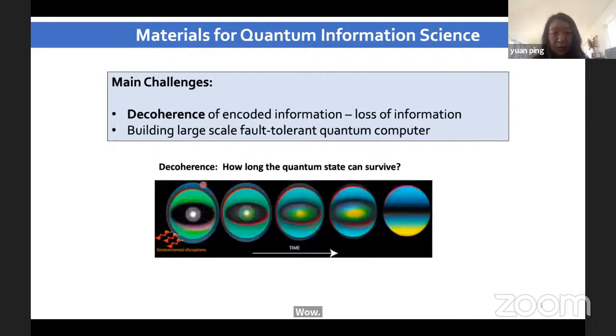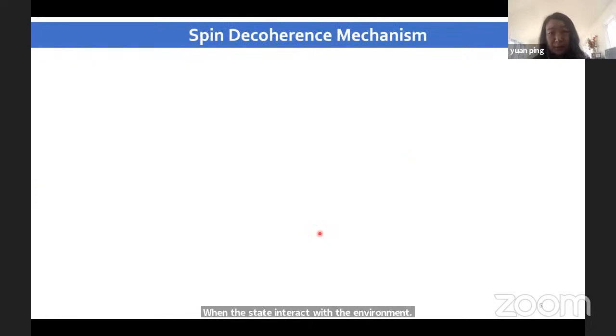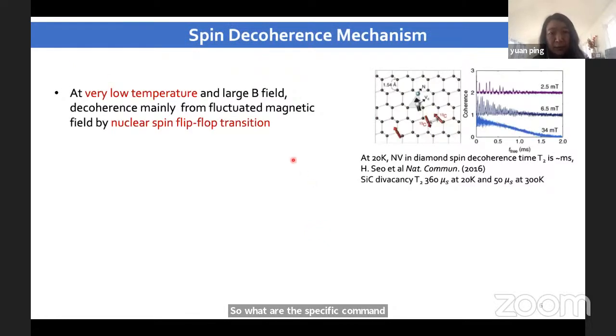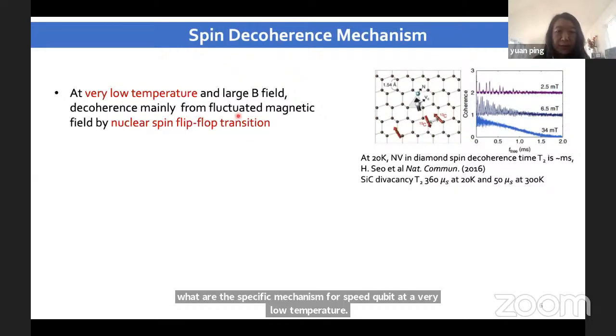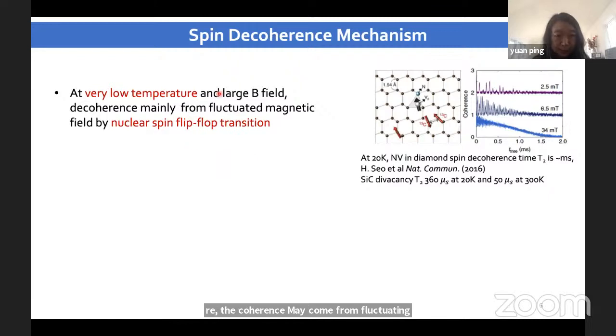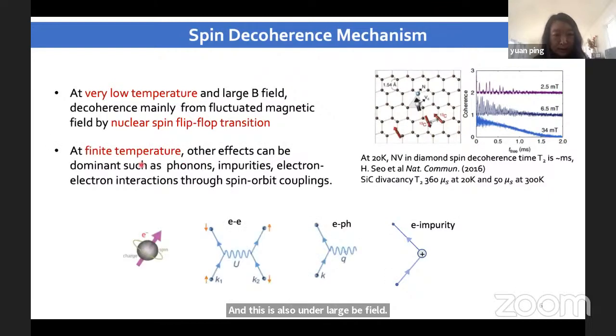One of the important challenges in this field is the decoherence of encoded information, where we lose information when the state interacts with the environment. So what are the specific mechanisms for spin qubit? At a very low temperature, decoherence may come from fluctuating magnetic field, and this is also under large B field due to the nuclear spin interaction. At a finite temperature, other effects may be important, for example, phonons, impurities, electron interactions through spin-orbit coupling, which will relate to spin.